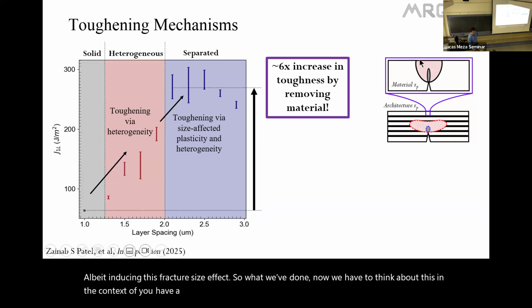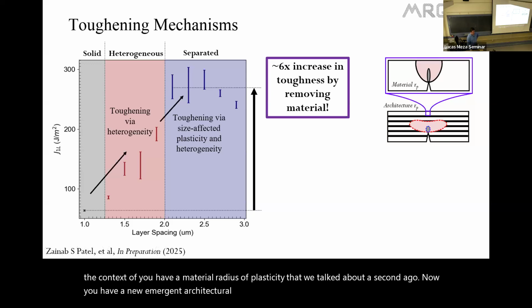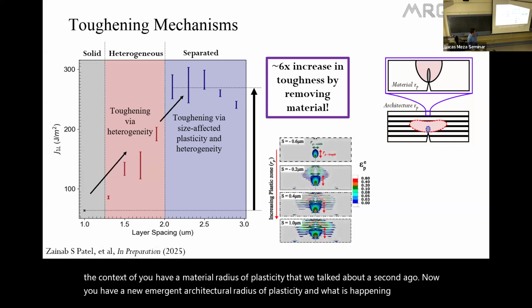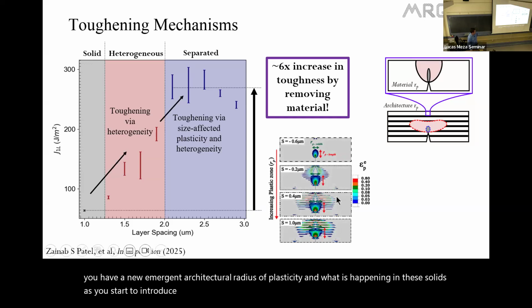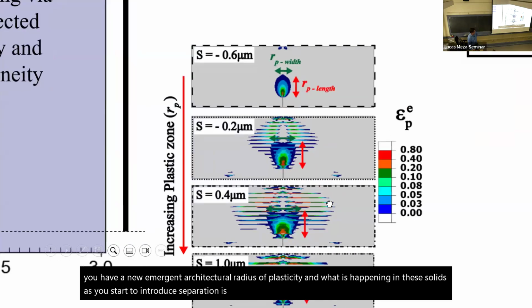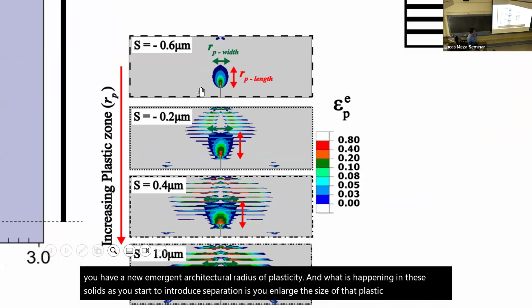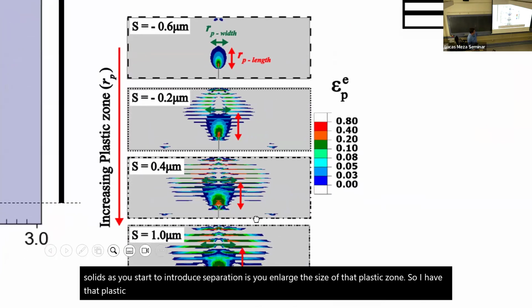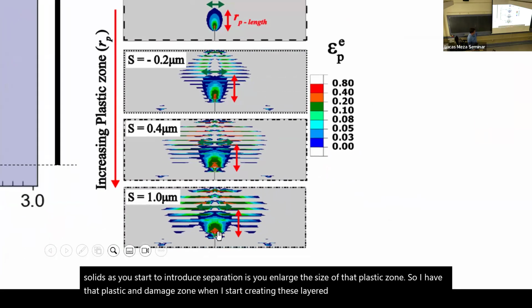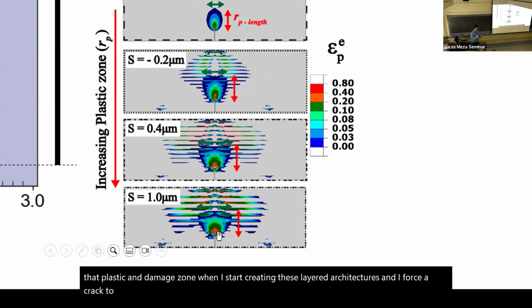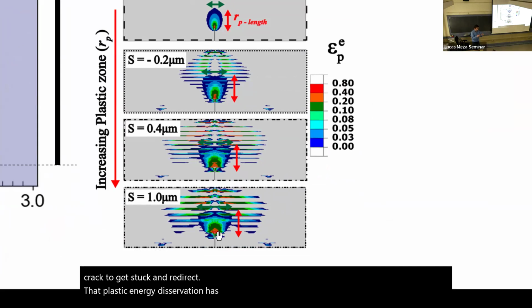So we have to think about this in the context of a material radius of plasticity that we talked about a second ago. Now you have a new emergent architectural radius of plasticity. What is happening in these solids as you start to introduce separation is you enlarge the size of that plastic zone. So I have that plastic and damage zone. When I start creating these layered architectures and I force a crack to get stuck and redirect, that plastic energy dissipation has to happen somewhere, and it ends up getting spread through the sample.